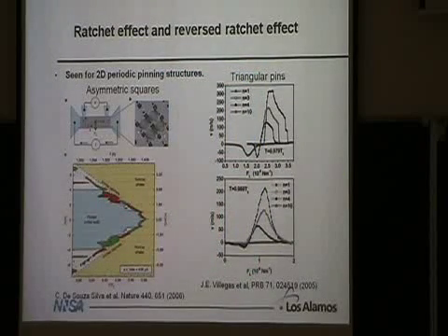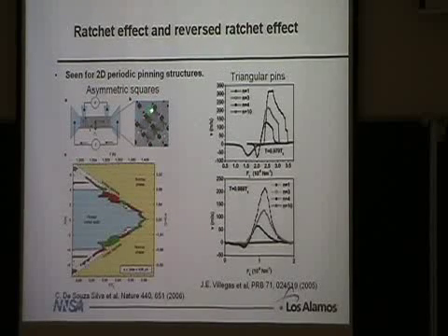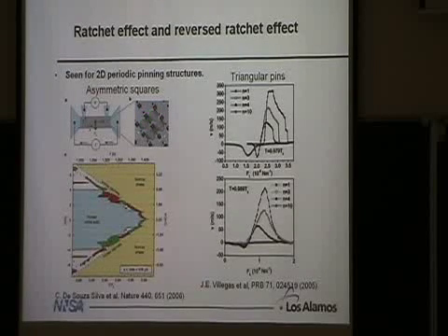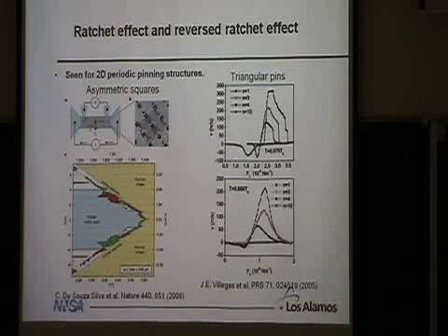Okay, so people have looked at superconducting systems to make ratchets. They made ratchets in a couple of ways. These are experimental examples. Here's an experiment where they artificially fabricated some pinning sites. They drilled holes in their superconducting film, one large hole next to one small hole. They put vortices on here and shook the vortices back and forth, and they would get a net transport of vortices. So of course they've broken a spatial symmetry and broken temporal symmetry, and they get a ratchet.